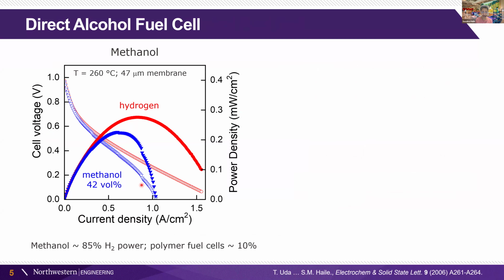And here's an example of our fuel cell operating directly on methanol. We can see that the hydrogen performance, as I showed you before, the peak power density is around 300 milliwatts per centimeter squared. And when we supply methanol, the peak power density is about 85% of what we achieved with hydrogen. In polymer fuel cells, the main competitor for ambient temperature fuel cell operation, that differential is very large, where the direct methanol fuel cells only achieve about 10% of the power output of the hydrogen fuel cells. That's because there's a lot of methanol crossover on the membrane, and you have to dilute that methanol extensively, whereas in our case, there's no methanol crossover, so there's no dilution required.